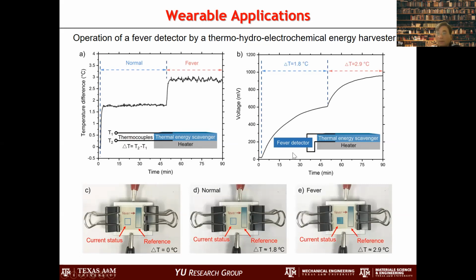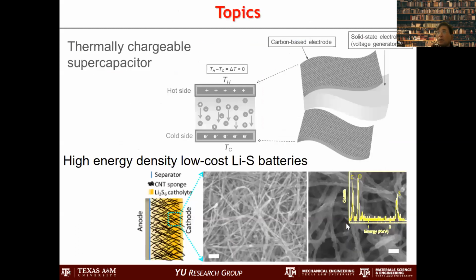So we demonstrated that this device can actually be used with only a few devices connected, and we can make an actual working device out of that. And this is what we have demonstrated. The interesting thing here is that the delta T is only 2.9 degrees C, not more than that. It's very, very tiny, but still we can operate this device out of this small temperature difference. So that's basically the topic that I want to cover.